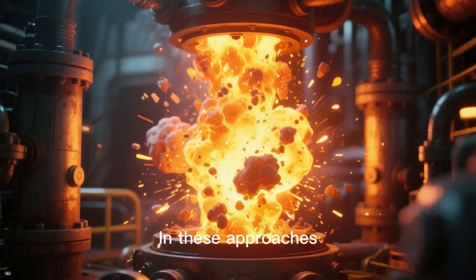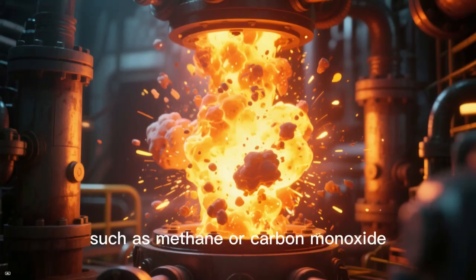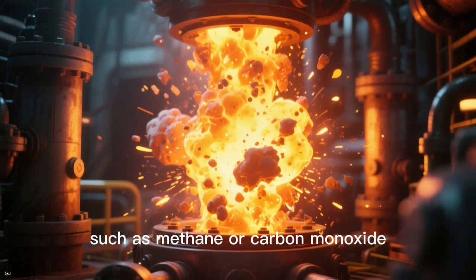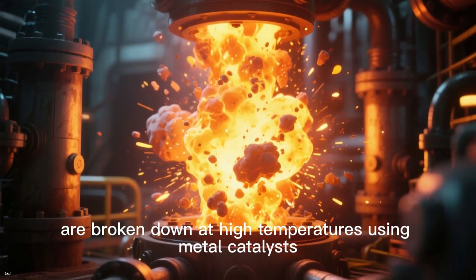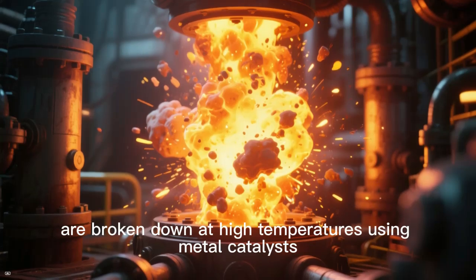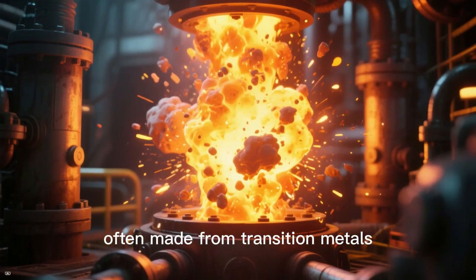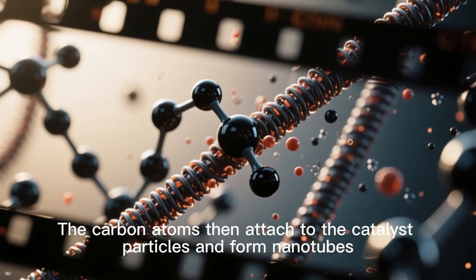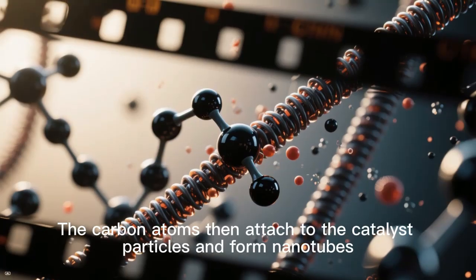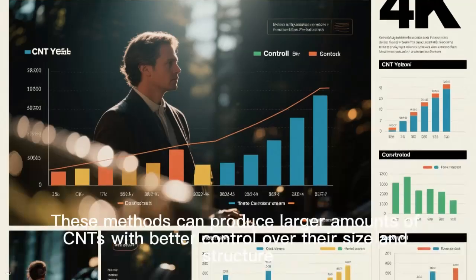In these approaches, gases containing carbon, such as methane or carbon monoxide, are broken down at high temperatures using metal catalysts, often made from transition metals. The carbon atoms then attach to the catalyst particles and form nanotubes. These methods can produce larger amounts of CNTs with better control over their size and structure.